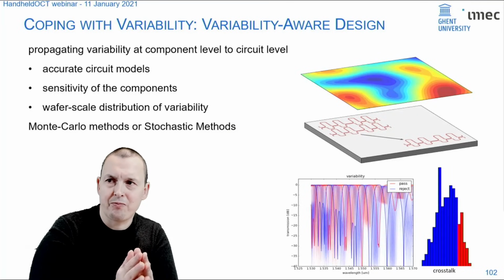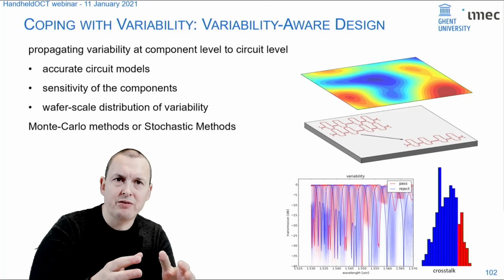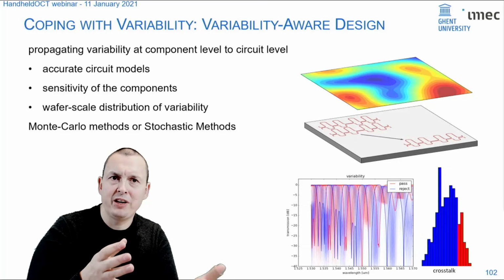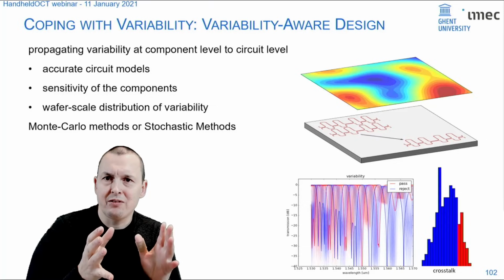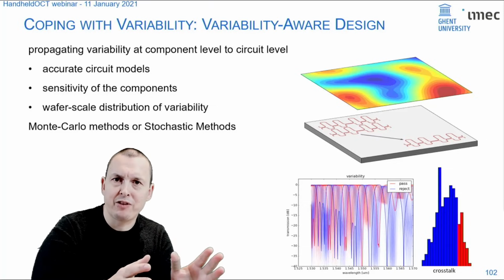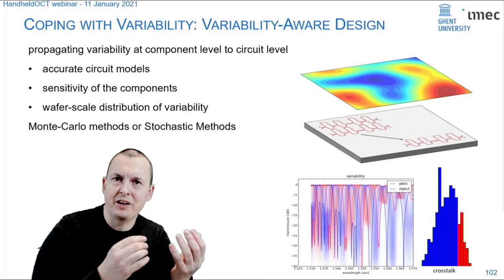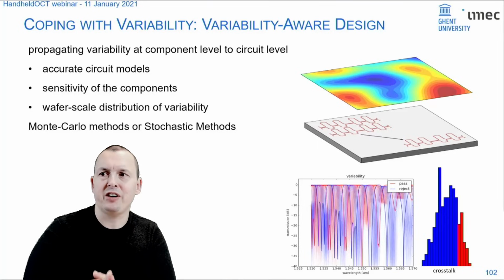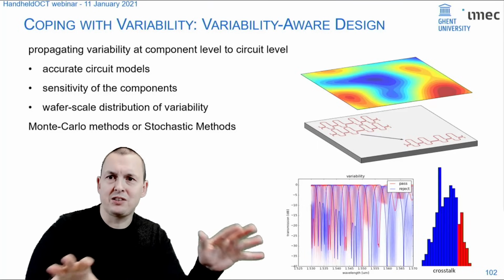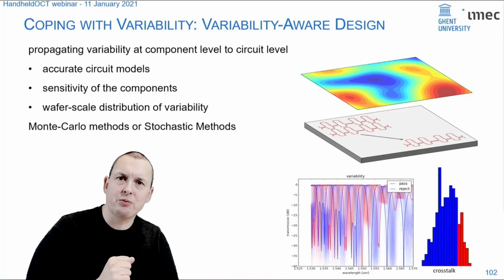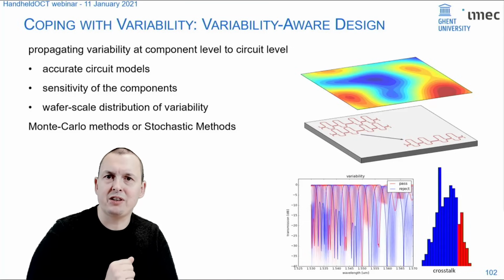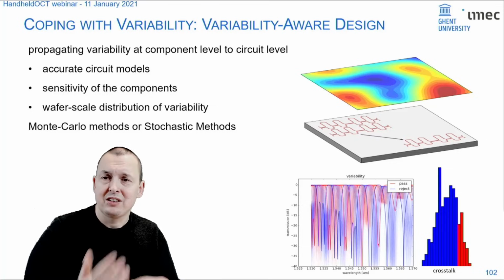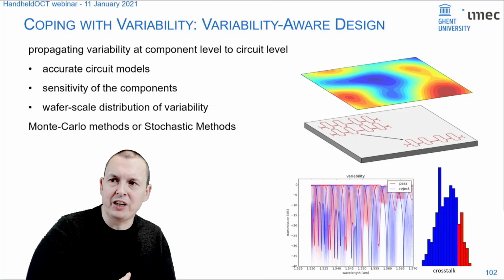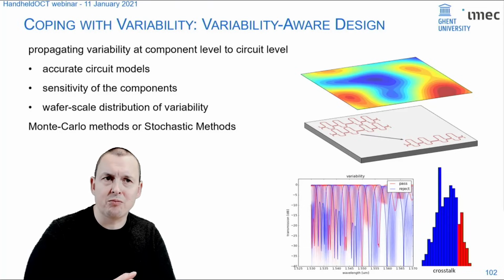Now, the second technique is going towards more variability aware design. And that's not that easy, because you need very accurate models of your devices, but you also need to know how they are being affected by different effects that happen during fabrication, like how sensitive my components are to line width variations and thickness variations. And you need to know how these quantities are usually distributed over the wafer. So what's a typical distribution pattern of thickness variation or line width variation? You can combine all that together using Monte Carlo techniques or stochastic techniques to get some form of yield prediction. But this is still in a very rudimentary stage in photonics.